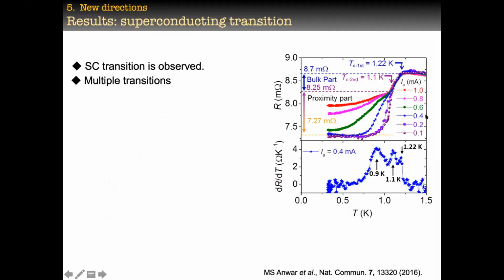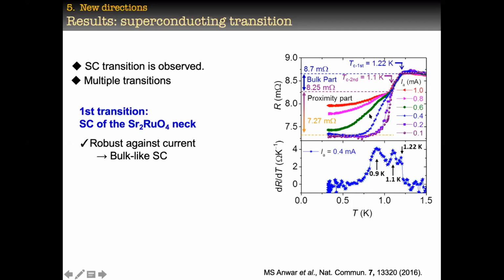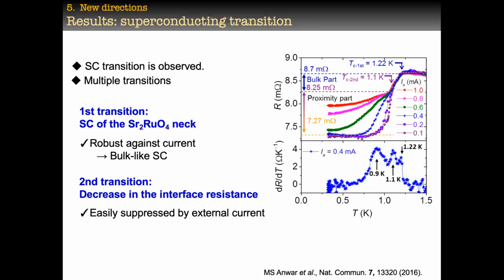Superconducting properties, the very first thing you can do is cool it down and measure the resistance. You can see this time I have a superconducting transition. When I do have a superconducting transition, one transition is quite strong and the other one is weaker when I increase the current. That means this weaker one is coming from the weaker superconductor, meaning the proximitized one, which is in the ferromagnet. So this actually shows that there are two transitions.